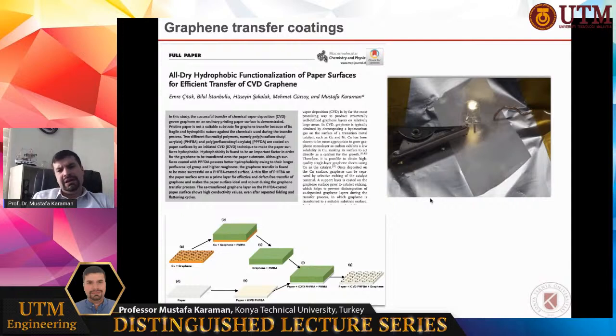But once you deposit the graphene on a catalyzed surface, you need to transfer it to a real-world substrate to make use of the excellent properties of graphene, which is the difficult part. So in this study, we functionalized the surface of paper with a hydrophobic material and transferred the graphene on top of that material. Because of this iCVD coating on the paper surface, the graphene transfer efficiency was improved very much. So we can transfer the graphene easily on top of the paper surface.